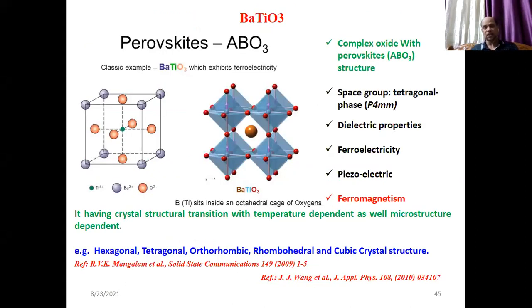Nickel zinc ferrite is a soft magnetic material. Barium titanium oxide is a perovskite, and it also shows a ferromagnetic signal when you reduce the size, although it is a dielectric material. As I told you initially, people are searching for the existence of magnetism together with the dielectric or electronic property, basically bound electron property and ferromagnetism together. So this material shows that property when you reduce the size, and it has to be explored in a better way for use.